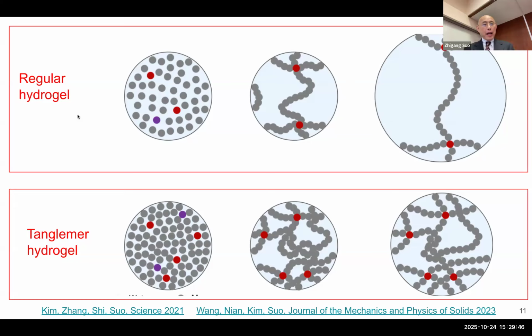All right. So now regular hydrogel, even in our group, we have been preparing this hydrogel for more than a decade. Remember, hydrogel has 90% water in it, right? So regular people make hydrogel this way. You have a lot of water in the precursor solution. How much water? For every monomer, a typical value is 20 water molecules. That works out to about 80, 90% water by volume. If you do that, the chains will be far apart. If chains are far apart, they don't have a lot of entanglements. Nobody talked about this fact before.